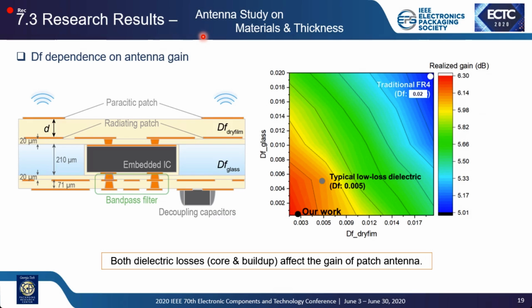So let me show you another set of antenna studies on DF dependence of antenna gain. So here is the radiating patch and the parasitic patch fed by aperture coupling. If you look at the antenna realized gain in the z-axis, which is defined by color, I tried to change the DF or loss tangent of dry film and glass, and if you use traditional FR4, which has a DF of 0.02, the gain is pretty low.